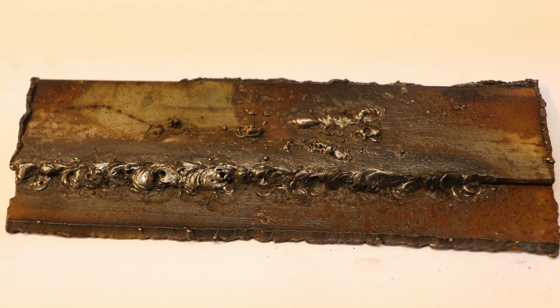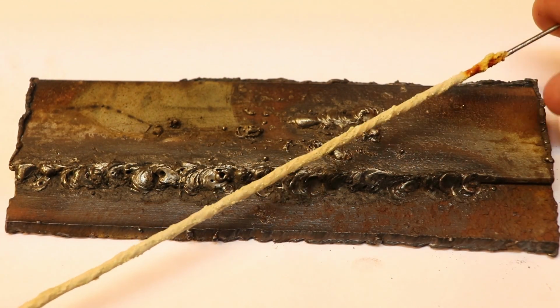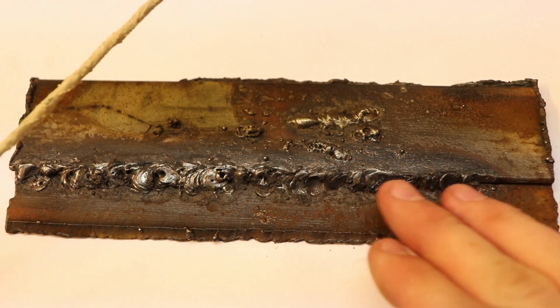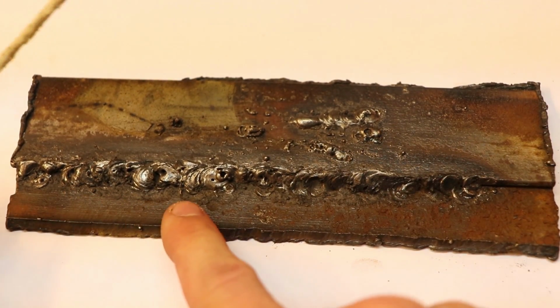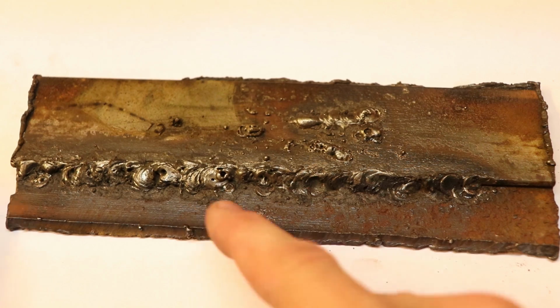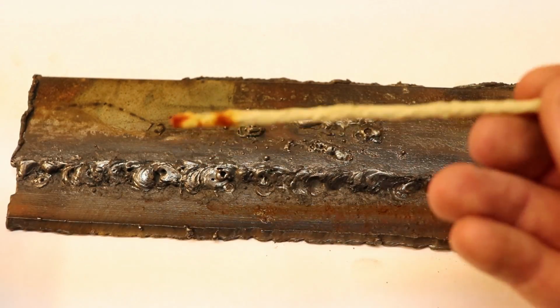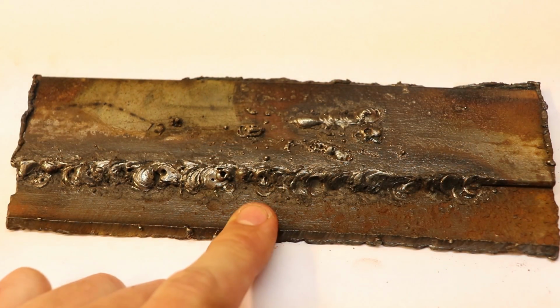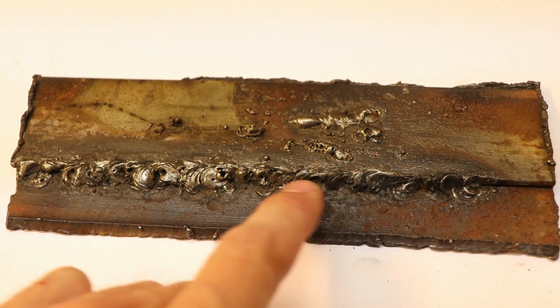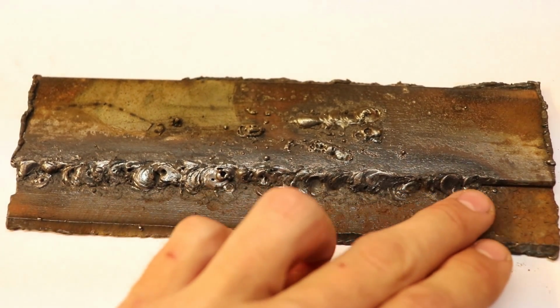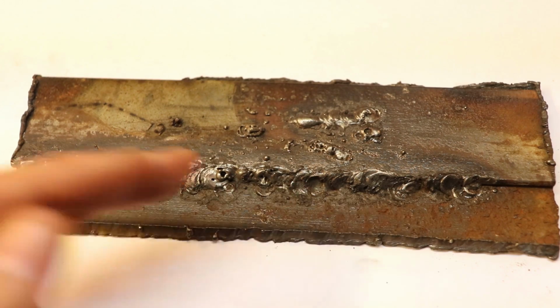So these are the 2 first plates that I welded with the homemade welding rods, and man, I am impressed. I'm honestly impressed. Maybe I'm too easily impressed, but these welds for a welding rod that I made myself are actually pretty consistent. You can see that we still have some porosity in the welds in the beginning here, but I was still trying to figure out how to properly weld with these. And then as you go along to the right of this plate, you can see the weld's getting more consistent, slightly better.